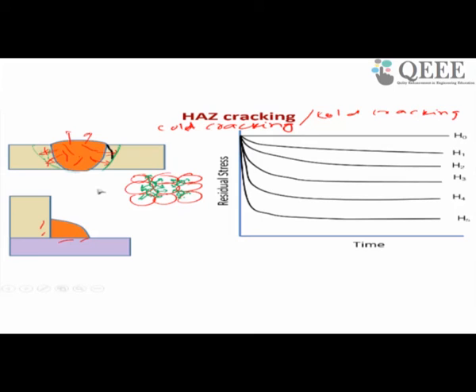Now, if a material has some residual stress, this residual stress will act as a driving force for crack initiation. So it will form a crack after a long time because of the presence of residual stress, and the crack will form and propagate near the heat affected zone region. That's why it is called heat affected zone cracking. You can see from this figure, H0 means no hydrogen content is available.